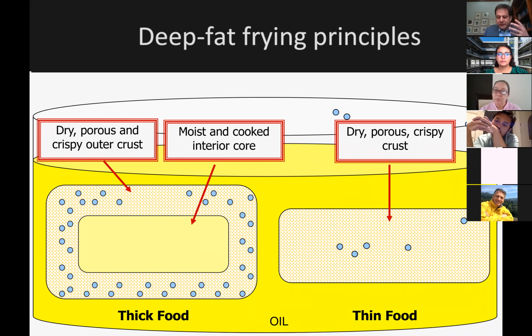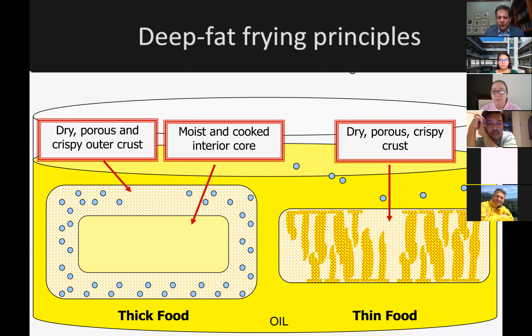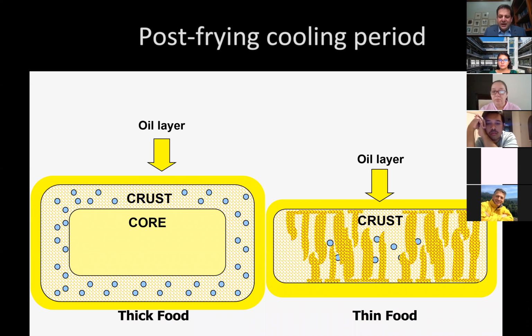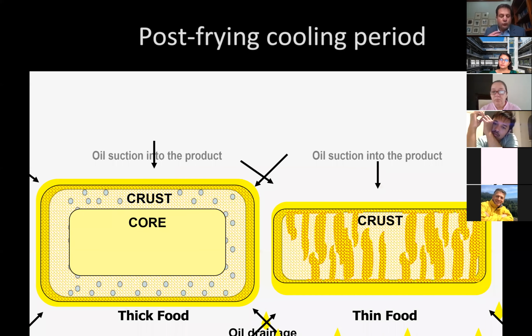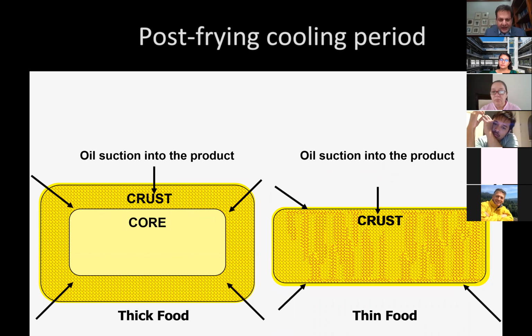And what I mean by understanding is that through different kinetic experiments that have been developed together with the microstructural approach that I will emphasize afterwards, we have been able to demonstrate within the group that as this evaporation of water is so intensive, the bubbling is so intensive during the deep fat frying that it really precludes and prevents oil from penetrating during the process, during the immersion. And we have been able to demonstrate that it mainly occurs upon removal of the food from the oil bath. And the oil layer that is deposited on the surface is finally absorbed within the porous structure once the product is removed from the oil. Some of the oil will drain, but some of the oil will penetrate within the crust as the vapor pressure decreases and the porous structure allows the oil to get within the structure.